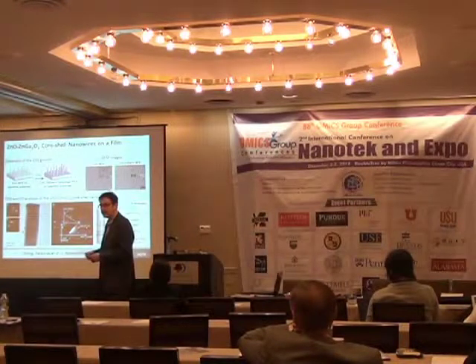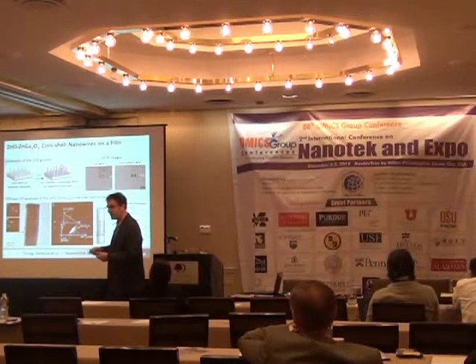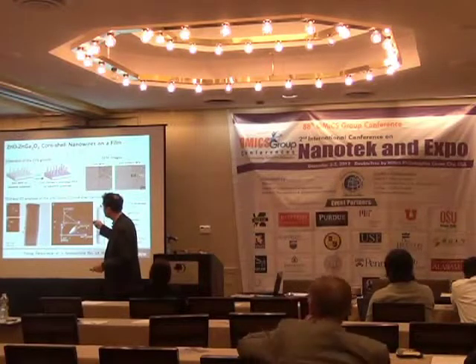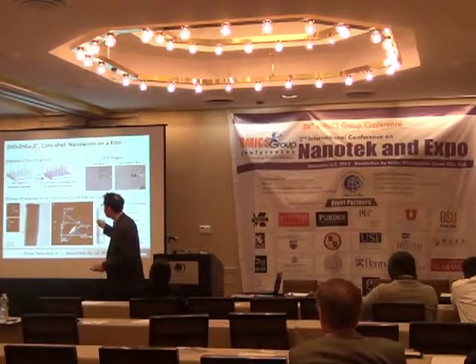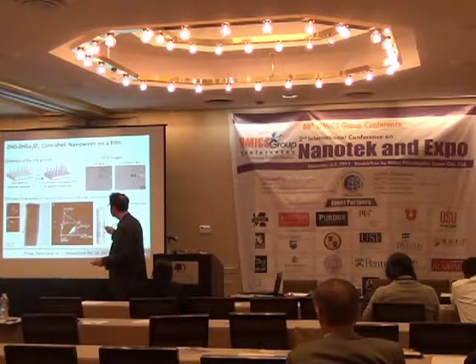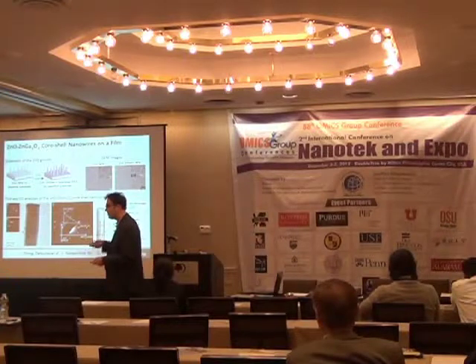Okay, so the next step now is we use the zinc oxide nanowire on film structure as a template to do this water splitting experiment. Zinc oxide is not very stable in water, so we have to protect it by covering it with a layer that is stable, and for that we use the zinc gallium oxide phase to fabricate a core shell structure. This is just a CVD process, growing this shell on top of the zinc oxide to protect it, because zinc oxide will dissolve in water if it's not protected.